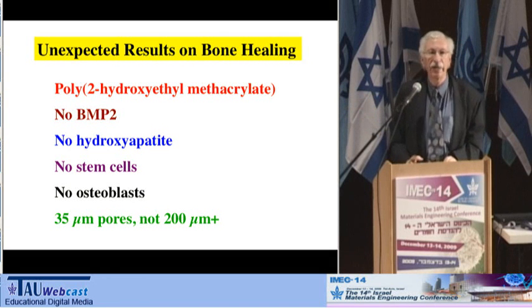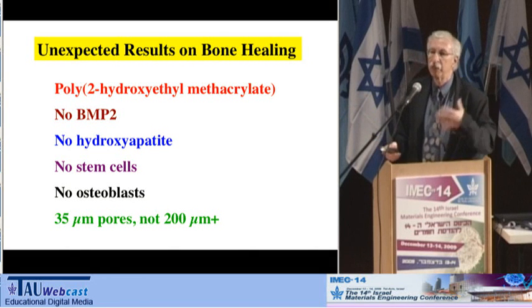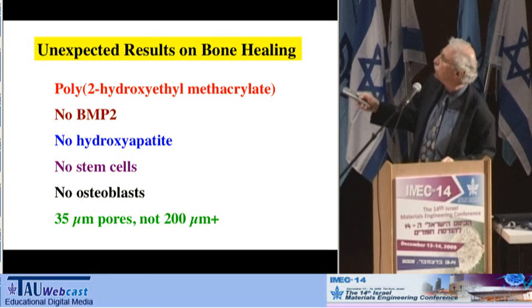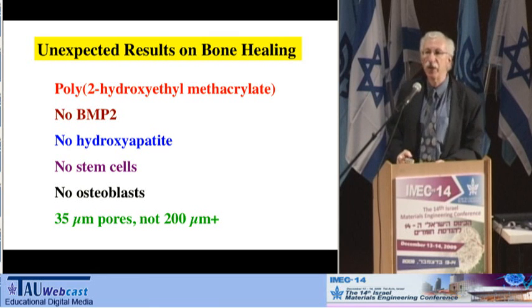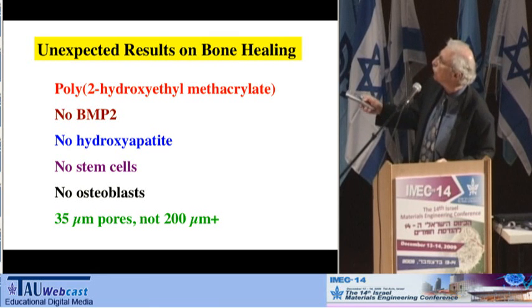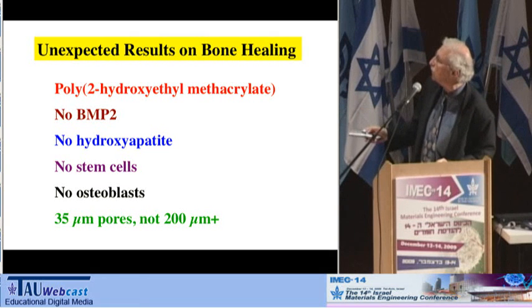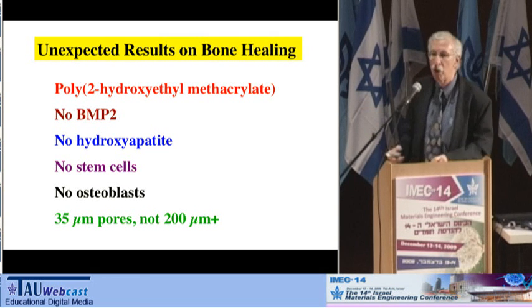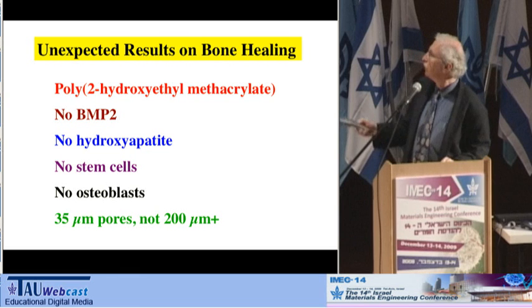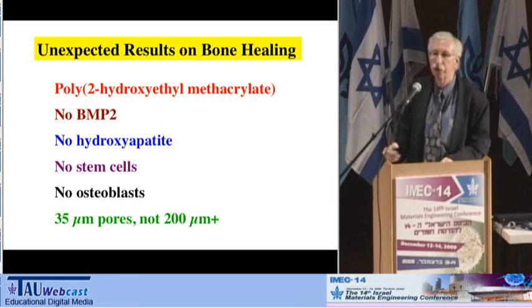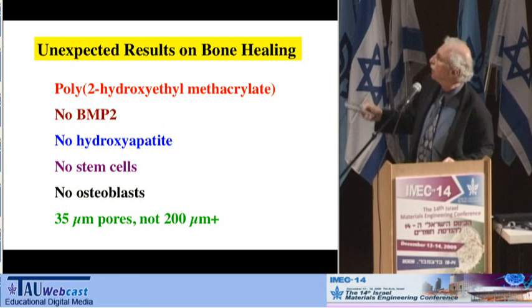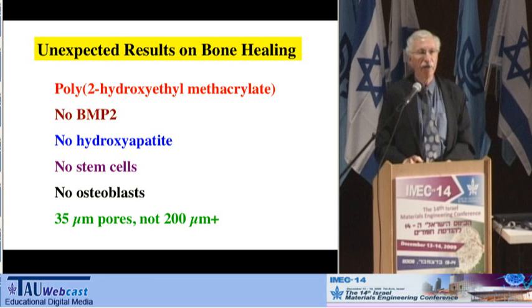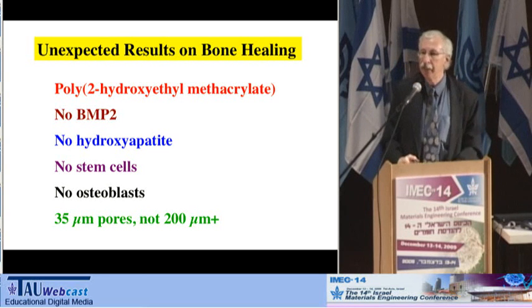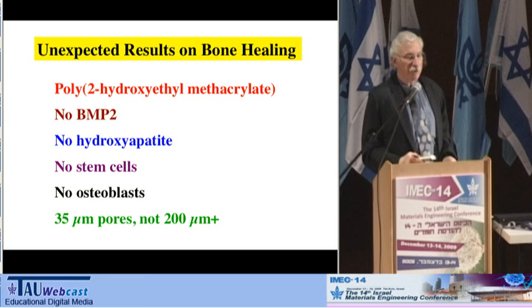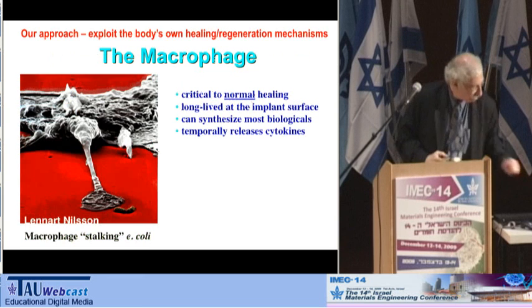We didn't use this cytokine BMP2 that many people are using to stimulate bone growth. We didn't use any calcium phosphate mineral phases to stimulate the growth. We used no stem cells, no osteoblasts. And almost everybody in the bone field feels you need pores greater than 200 microns, and we use 35 micron pores. So this kind of defied almost every conventional wisdom in bone healing, and yet again talks to the regenerative capacity of this type of material.